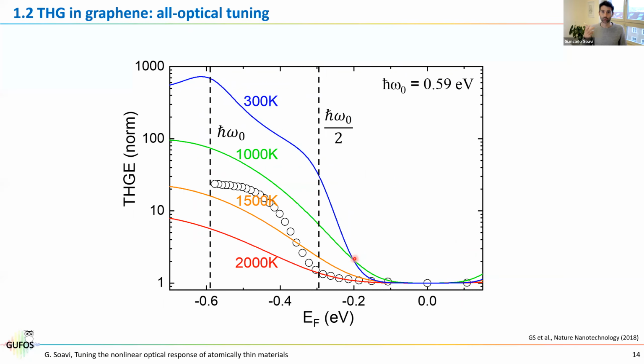So let's try now to compare again the theory with our experimental data. The circles on this graph are the same experimental data that I was showing you before, but this time I overlap it with the theoretical curves for different values of the electronic temperature. The 0 Kelvin, I don't even consider it because I was performing the measurements at room temperature. So our benchmark should be this 300 Kelvin. However, you see that our data fit better with electronic temperatures in the order of thousands of Kelvin.